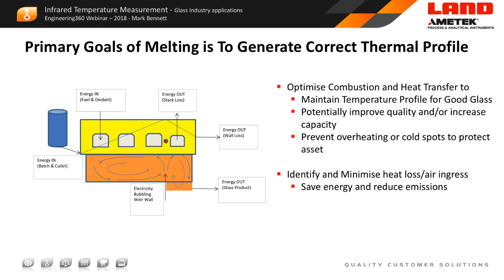Now, when we look inside the glass tank, we have to recognise this is a very complex thermodynamic model, and the glass flow within the glass tank is absolutely critical. You can see in my diagram that we show the glass circulating under the surface in two different directions. And we create something called the spring zone, where the glass comes to the surface. The basic melting and dissolving of the glass occurs in this region, and this section here is more refining and removal of gas from the glass composition.